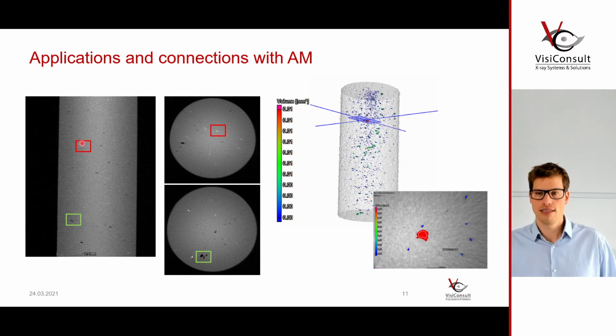And what you can see here is different inclusions. These are the white dots. You can see porosities, and you can see that in some areas these porosities are quite severe and will potentially affect the load capacity of that part.